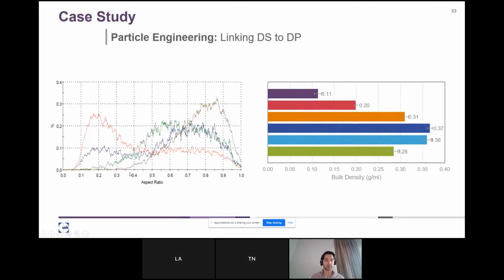And here you can see the shape factors. Here is the aspect ratio, the ratio between the longest dimension and the shortest dimension of the crystal. You can see that a lower value means the crystals are more needle shaped. This is the initial crystal that we had, and this is the engineered particle that we have, where the value goes towards 1, which is more like spheres, or they have the same equidimension.